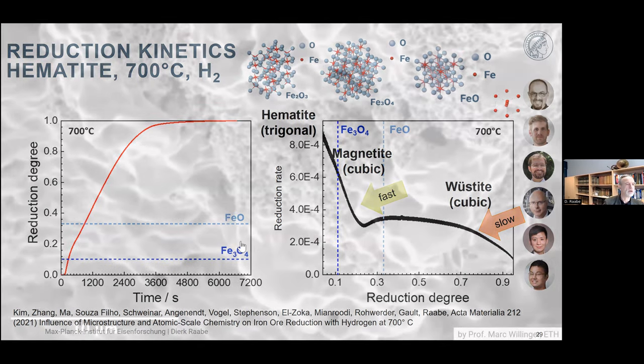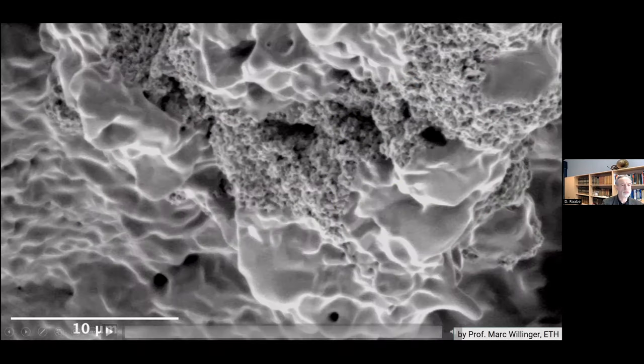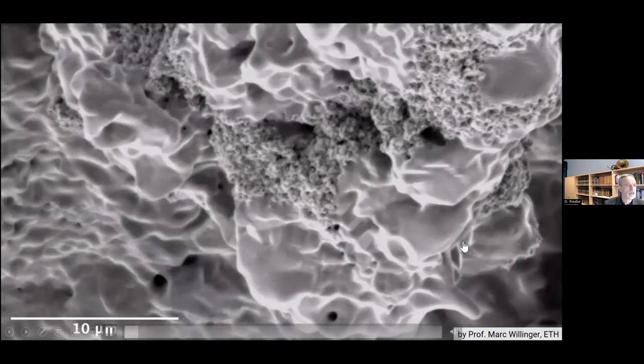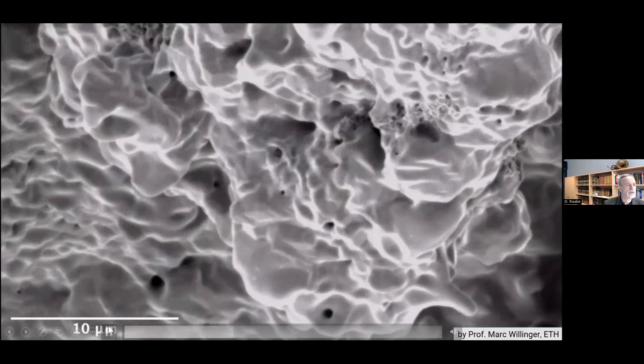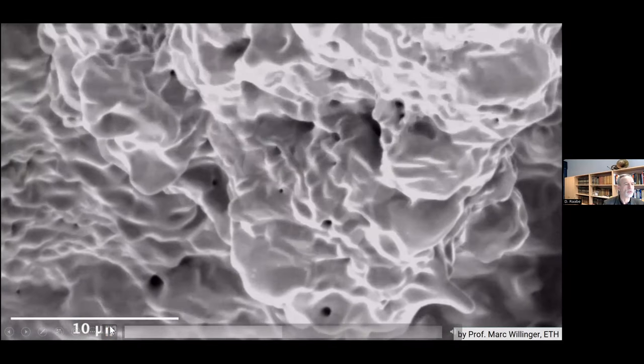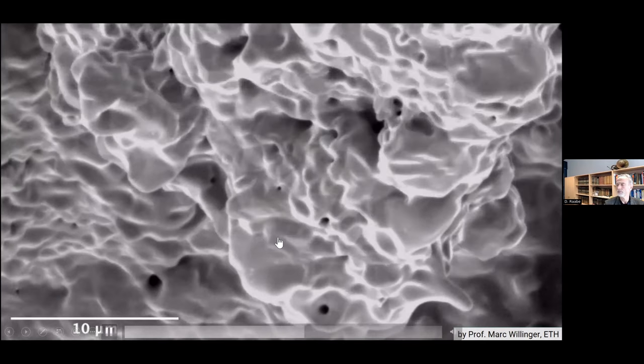Here you see a movie that we did 2 years ago with my colleague, Professor Mark Willinger, in an environmental microscope. That means the electron microscope is flooded with hydrogen, and you see this rough-appearing surface that is a wüstite single crystal. So we look only at the last stage. And you can see here that this, when exposed to hydrogen in the electron microscope, is now readily overgrown by this thin solid iron film.